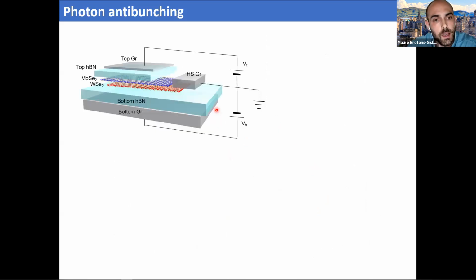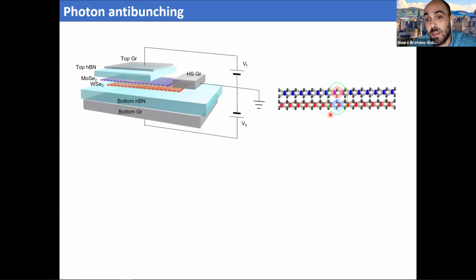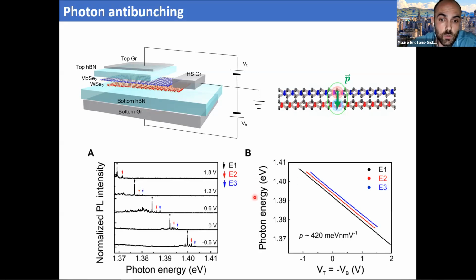But I'd like to show you something else. If you think about it, these interlayer excitons are interlayer, which means that we have the electron and hole in different layers, right? So that means that we have a large permanent out-of-plane dipole. So in principle, by applying a vertical electric field, we should be able to use the Stark effect to tune the emission energy of these excitons. And here is what happens when you do that. I'm showing here the spectrum for a few of these quantum dots, where we change the applied electric field. You see that I'm applying a bit more than 2 volts, and with just 2 volts, I'm able to tune the emission energy of these quantum dots by almost 40 milli-electron volts.